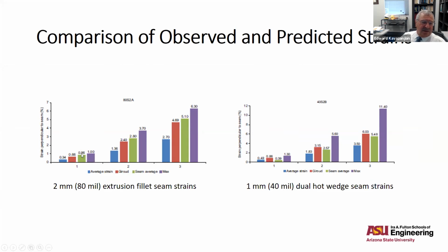This is what we measured around the seam. And this was the maximum, the high points in the seam. When we looked at the individual pixels and picked out the maximum seam strain, this was averaged over the length of the seam in the middle half of the coupon. This was the maximum over that side.